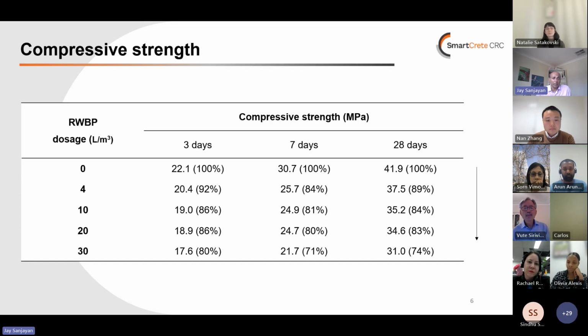So as we can guess, I think it's better if you focus on the last column, 28-day strength. This is a 40 megapascal strength mix design. But despite we pull off some water, the amount of air introduced is so high, there is reduction in strength. So that is an issue.